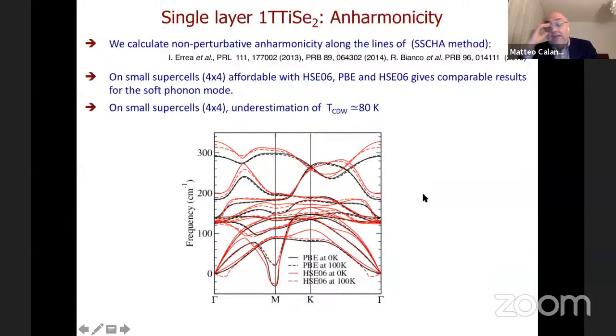However, it is well known that such small supercells tend to underestimate the effect of anharmonicity, but the outcome of this calculation is that even if the effect of anharmonicity is underestimated, it's practically identical in PBE and HSE06, so I can go on only with PBE, which is one order of magnitude less expensive than HSE06. I forgot to tell you that those calculations are done with Gaussian basis sets, because of course HSE06 with plane waves on this kind of system is totally unaffordable.